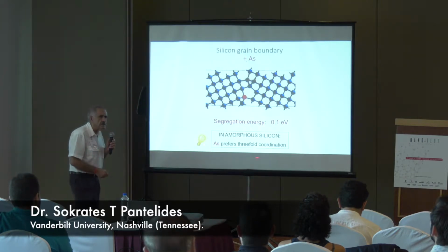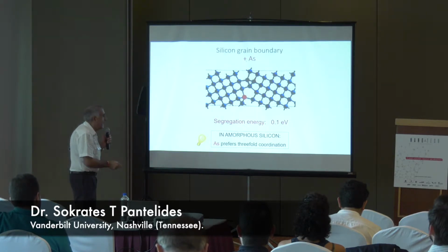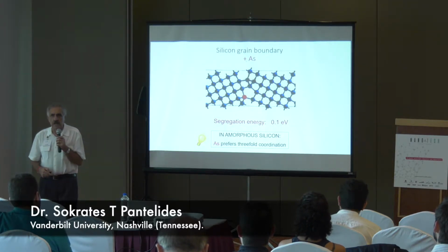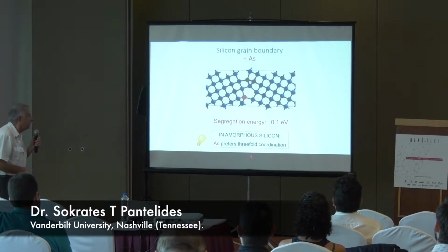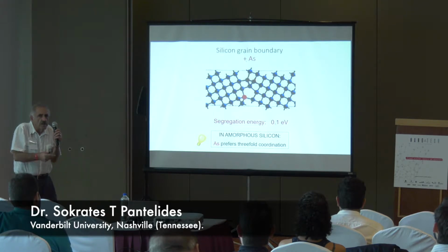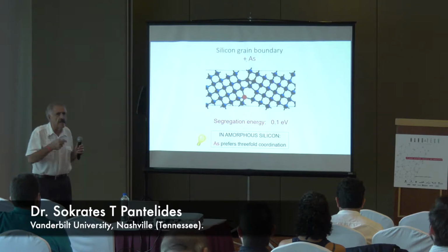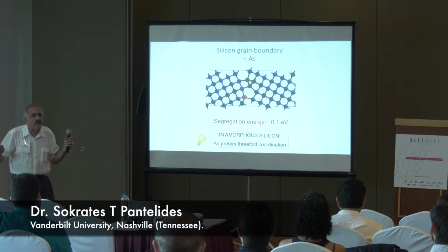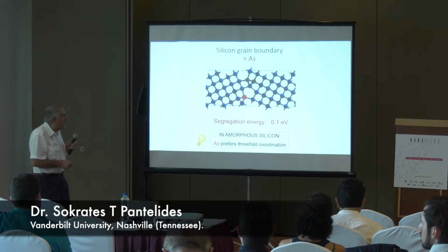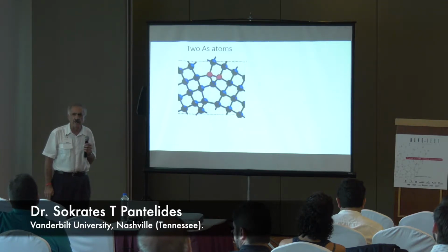Then we had an idea. You need ideas in research. Without ideas, you're not going to go anywhere. All right? And I knew, I had worked in amorphous silicon, that when you try to dope amorphous silicon like that, because of the flexibilities in there, arsenic prefers 3-fold coordination, because it has 5 electrons, 2 of them become non-bonding electrons, and 3 neighbors. Right? Phosphorus, arsenic is like nitrogen that makes NH3, ammonia. It needs 3 neighbors. All right, so the problem is now, how would an arsenic going in there get 3 neighbors if everybody has 4?